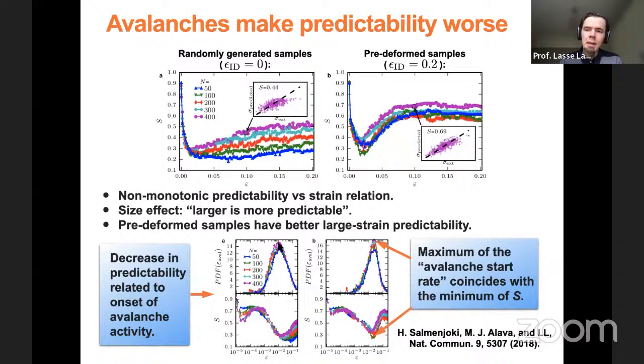The funny thing here is that this maximum in the number of events that are triggered actually coincides with the minimum of the predictability. The idea is that these avalanche events are inherently unpredictable things. So if you get lots of those, then it's hard to predict, right? And that's why you would get this minimum in your predictability.